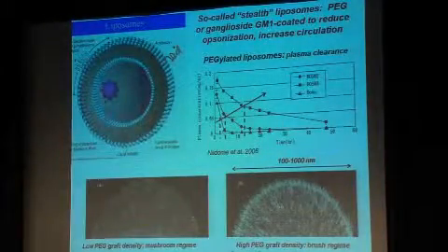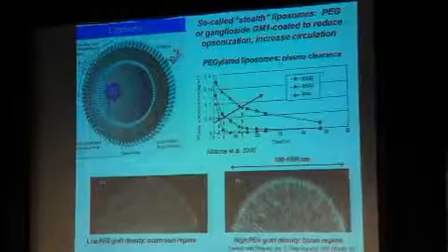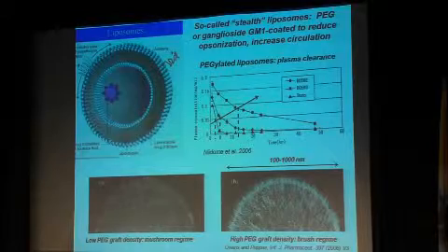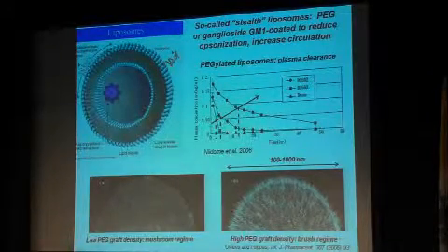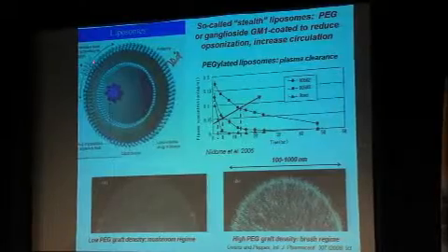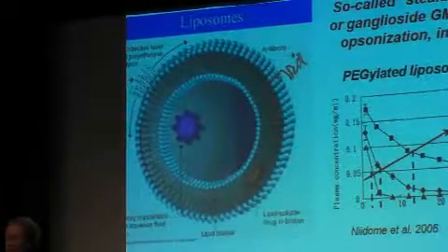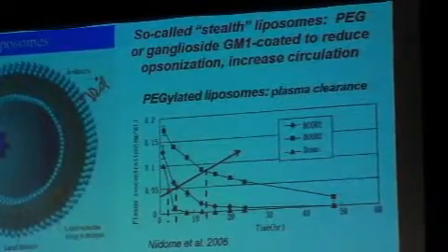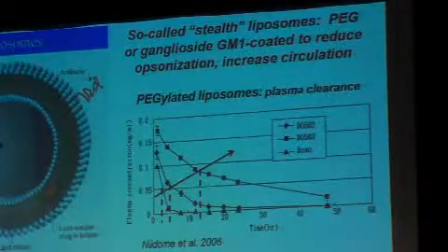All right, so there have been many ways to try to eliminate this aggregation behavior. And one of the common models, again, if we go back to the liposome, because this is FDA approved and involved in several products, the idea is to decorate the surface of the liposome with hydrophilic polymer chains that act kind of like seaweed. And the seaweed is out there waving, preventing the adhesion of these particles to undesired sites. So we decorate the surface with these hydrophilic polymers, and one of the common ones is polyethylene glycol, PEG. And pegylation is a term that we use technically to describe the addition of these hydrophilic coronas around nanoparticles.